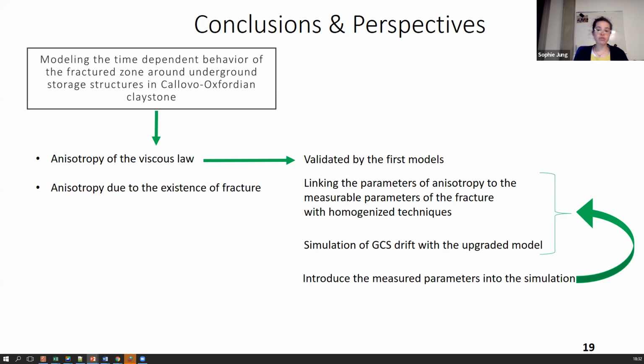Then we improve the models by explicitly linking the anisotropy parameters to the fracture parameters. And finally, the objective will be completely achieved when we can feed the numerical simulation by zone with the experimental results and with our more detailed comprehension of the behavior of one fracture.